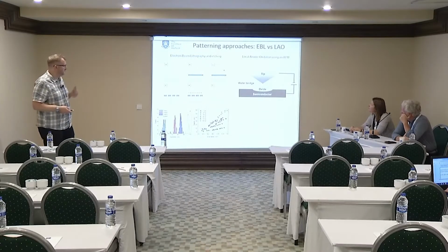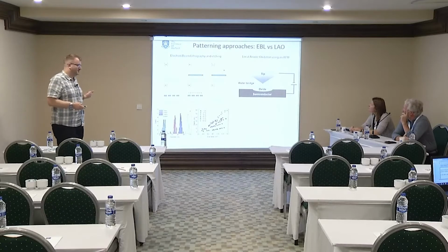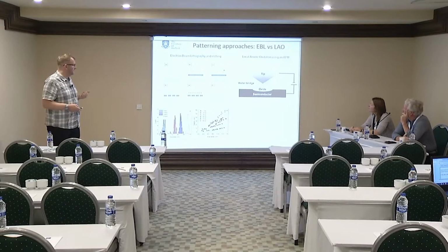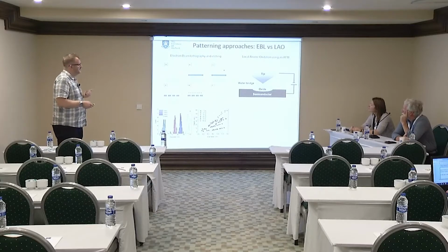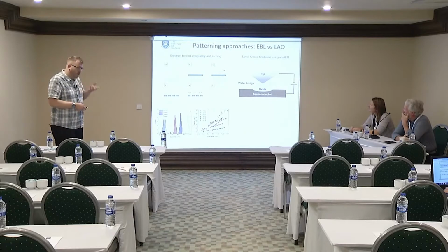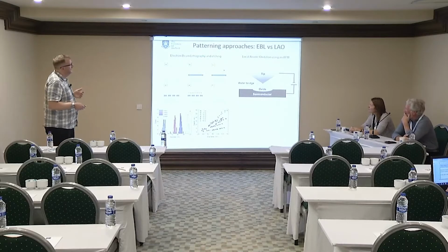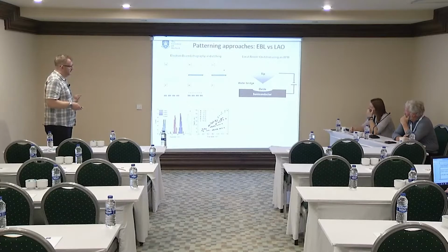The alternative approach, good to get a student started whilst they're waiting for the MBE machine to arrive, and also good when the E-beam is down, is oxidation using an AFM tip. In a warm and humid environment, ideally controlled, but at least works well in summer, not so well in winter, you have a water bridge that forms between the tip when it's brought very close to the surface, and if you bias that, then you end up forming an oxide. And that oxide grows up and goes down into the semiconductor.